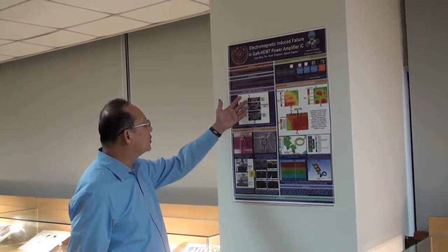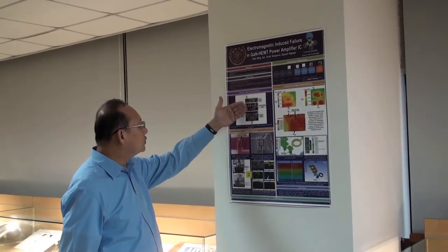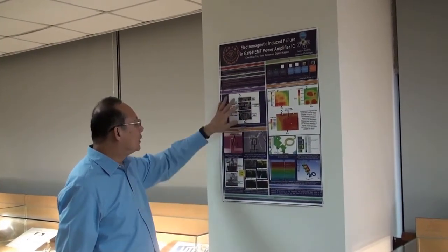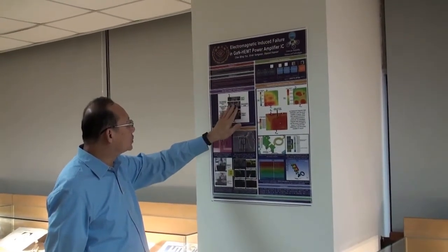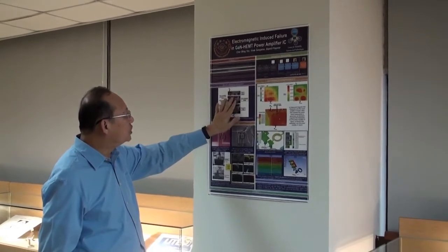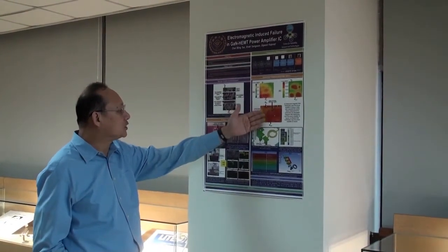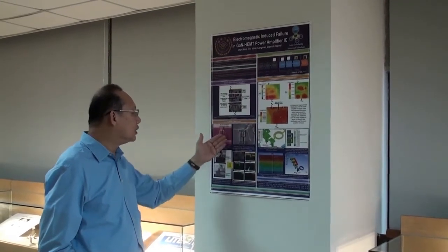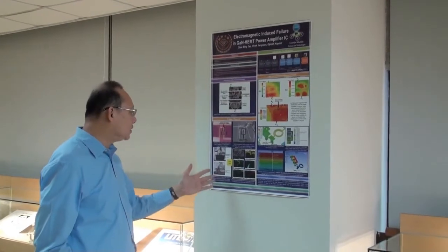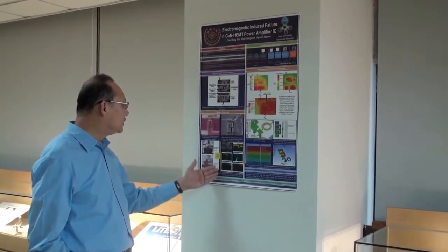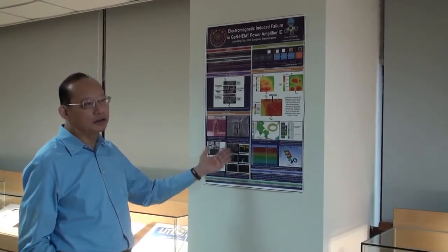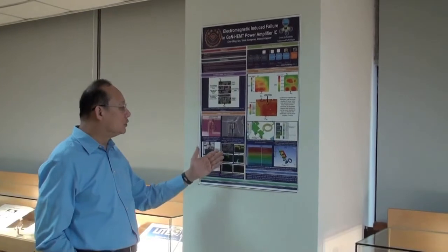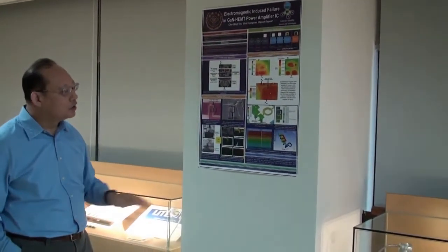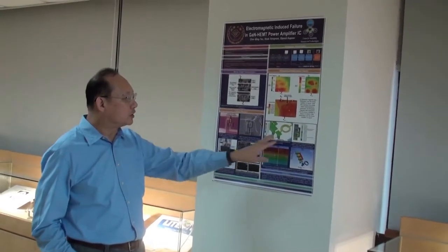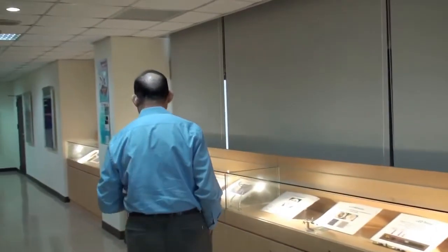This new failure mechanism is really because of the magnetic field coupling together with eddy current. The magnetic field couples through one of the transistors in the intermediate stage, and this magnetic field will induce eddy current onto the plate, whereby it increases the current and increases the heat so much that it actually melted the metal on top. And this is very surprising. In fact, the temperature is so high that even the underlying gallium nitride will decompose, and the gallium comes up from the bottom to the top, where we can actually observe it in the SEM. So this is a very new failure mechanism, and we also did a simulation of the eddy current to see how it failed.